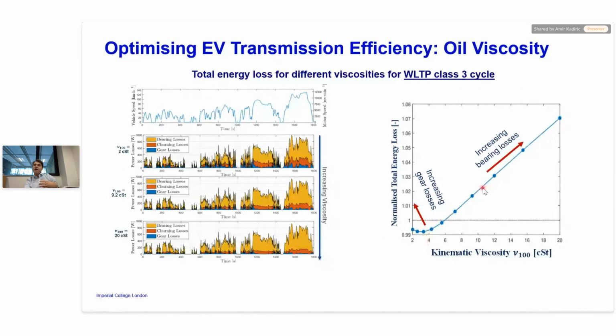If you go any higher, what happens, you can't quite see here, but the bearing losses go up. Bearings like low viscosity oil, so it's not good. If you go higher this way, your gear losses go up. There's an effect on churning losses as well, but gear losses go up. So going down to some crazy low viscosities of 2 centistokes, 1 centistokes, is not going to help you. And that was quite an important result here.